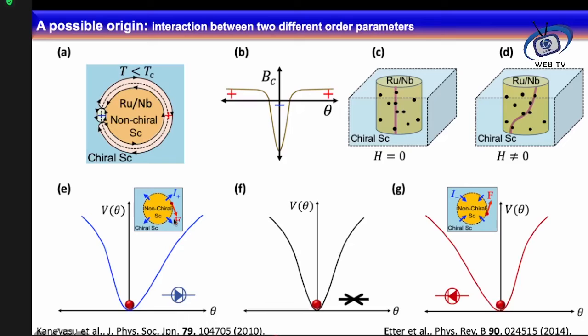So you can explain this diode effect: it can be forward biased, it can be reverse biased, or it can be simply a standard junction, which totally depends on the pinning potential configuration of your spontaneous vortex state. And this vortex state can change if you apply a magnetic field. Then it will be distorted, and it will select a random configuration of your diode. So these are our very recent results. They are under consideration in Nature Communications, and I hope they will be published soon.